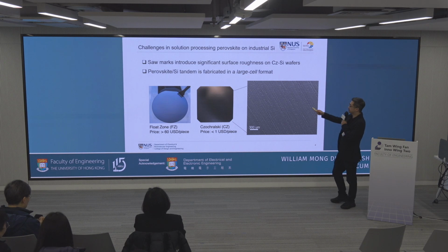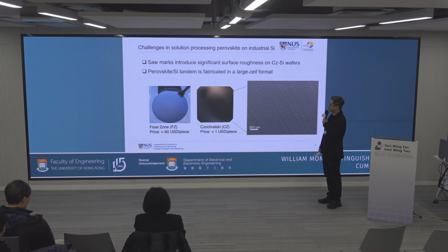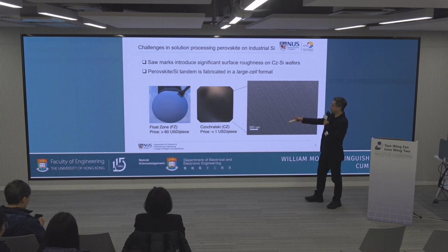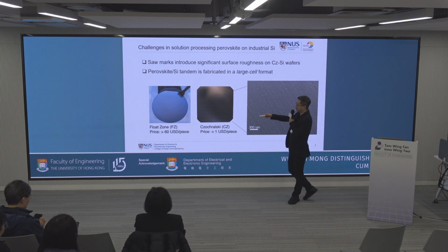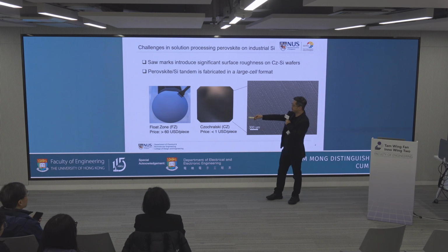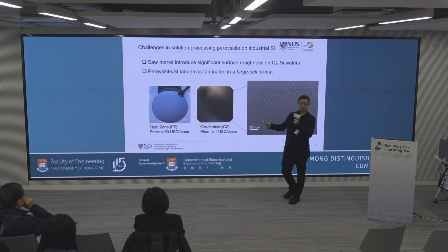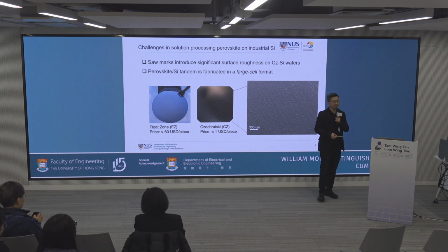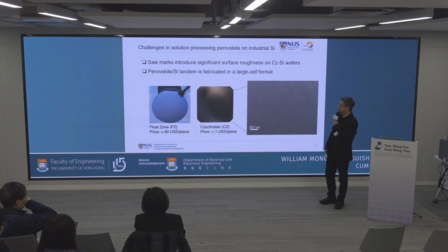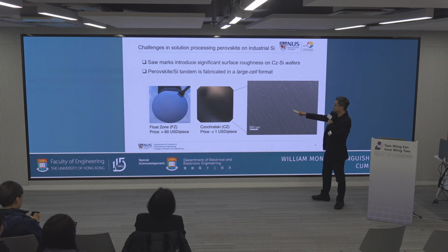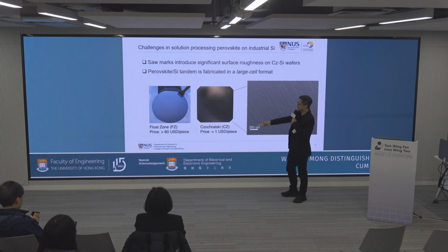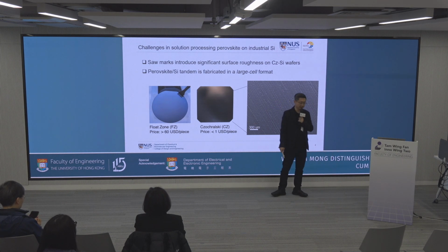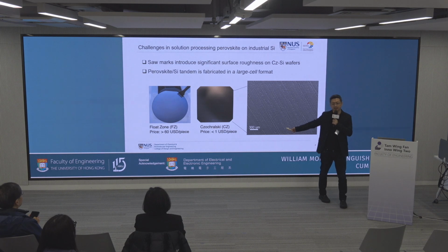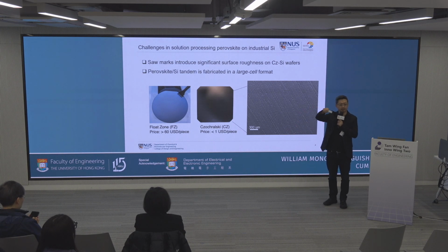If you look at this, you can see two big challenges here. One is, normally when we make small area solar cells in the lab, we use this so-called float zone wafer. Actually, this wafer is for the semiconductor industry. It's for the transistors, for chips. And it's very expensive, as you can see, more than $80 per piece. For the solar cell industry, no one uses this silicon wafer. Everyone uses CZ wafer. CZ wafer is very cheap. That's the one you see outdoors, on the solar panel on your residential rooftop. It's using this CZ wafer.